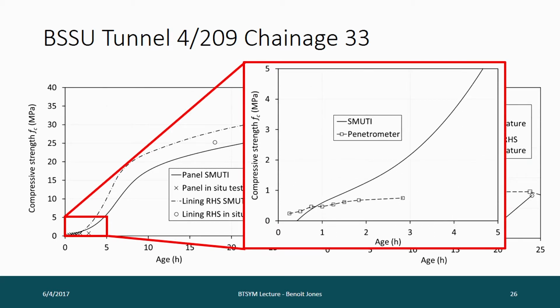If we focus here at the beginning, and this is the worst example I could find, this just shows the penetrometer results against the SMUTI results. And very early on, you can see the penetrometer is giving higher results than SMUTI. And that's partly because on this job, this was May last year, we had quite conservative assumptions about the initial strength provided by the accelerator and the initial degree of hydration and things like that. So we were being quite conservative with the SMUTI.